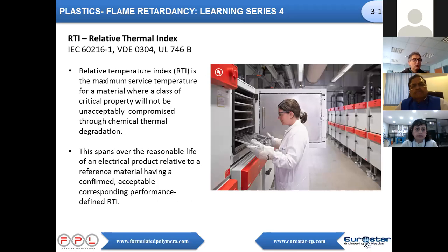So it's measured according to standards, of course. Relative Thermal Index, temperature index, sorry, is the maximum temperature service that the material can survive, let's say, for an infinite period of time. Of course, nobody can simulate an infinite period of time, so UL has a method to test with time equivalence temperature, where we can forecast for 60,000 hours.